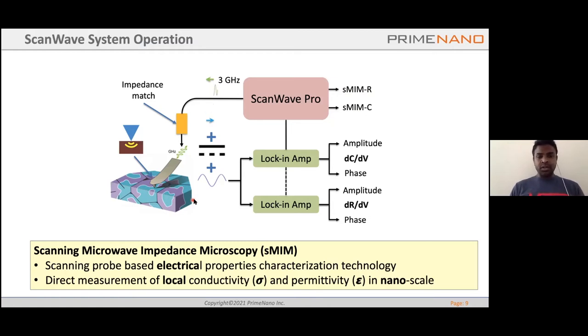Now further, if you have a sample which is non-linear, where the capacitance or the resistance changes with respect to the applied voltage, you can apply an external bias and also connect to a lock-in, and you can look at the amplitude and the phase of the variation of the dC/dV, or the variation of capacitance with respect to the applied voltage, or the variation of resistance with respect to the applied voltage. For a semiconducting system, this dC/dV represents the magnitude of the carrier concentration, and the phase represents the polarity, whether it's an N-type carrier or a P-type carrier.